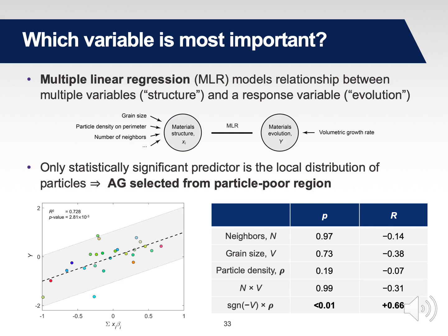So you have this very strong correlation due to the particle density. That is to say, again, that the spatial distribution of particles determines the size distribution of grains. To support these results, I should mention too that we conducted dimensional reduction through lasso regularization as well as an ablation study, which we describe in our Acta Materialia papers, and I provide a reference for this later on for those of you who are interested in learning more.